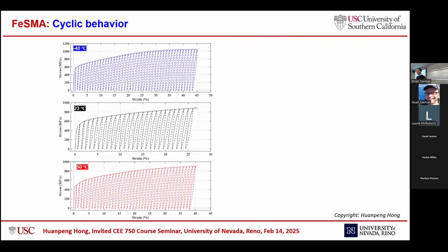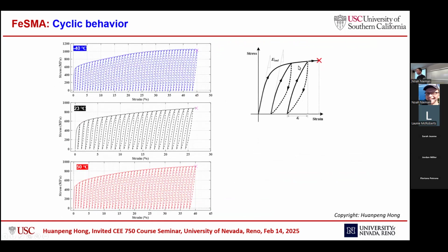Here's the cyclic stress strain curve of it. What we did here is apply 1% increments until failure: loading it to 1%, unloading, loading it to 2%, and then unloading, until the fracture of this material. At all three temperatures, from -40 Celsius to 50 Celsius, this material still exhibits really good ductility.